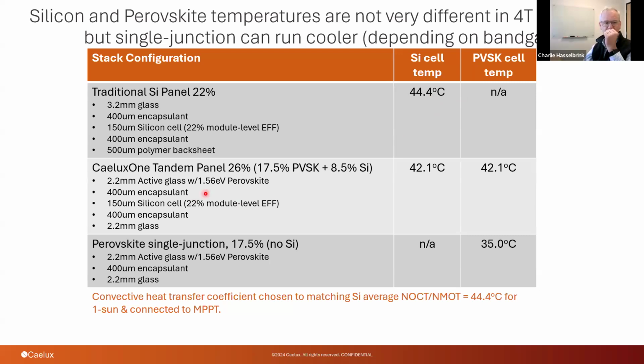The CaeluxOne tandem panel that we're aiming to release in early 2026, maybe a 26% panel, will have the 17.5% perovskite, 8.5% efficient silicon with these band gaps. And in that calculation, there's almost no difference between the silicon cell and the perovskite cell temperature. However, you notice the temperatures are slightly lower than the silicon cell temperature, and that's because of the efficiency. If we're getting 26% efficiency instead of 22, that means 4% more of the irradiance is converted to electricity, resulting in a lower temperature panel.